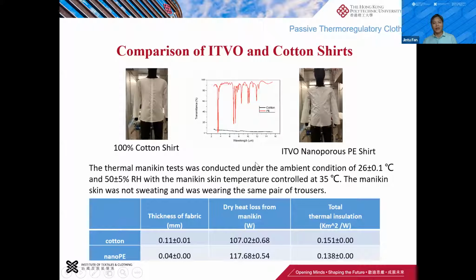mannequin, and we set the mannequin completely non-sweating, a dry mannequin. We conducted the experiment at 26 degrees Celsius and 50% relative humidity. We set the mean skin temperature of the mannequin at 35 degrees. And then you can see indeed this thermal radiative nanoporous PE should have about 10 watts more heat loss, okay, compared with the cotton shirt. So it has more cooling effect.